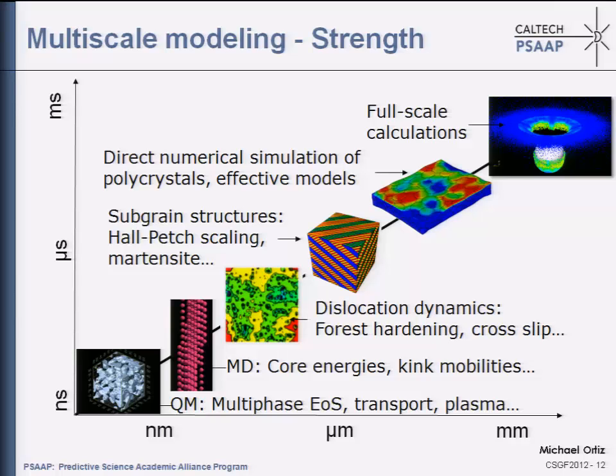So say, for instance, you're trying to characterize the strength of materials. Okay, so how do materials deform at high levels of stress and temperature and strain rate, for instance? Your global simulation may be at this level, so now you start looking down length scales and time scales. In a typical metal, you begin to see the polycrystalline structure. So you see that, in fact, these material points are not points at all, but themselves have quite a bit of structure. The first level you encounter at the SEM level, for instance, is the polycrystalline structure. Then if you look within individual grains, you find that the behavior of each one of these grains is in fact far from being homogeneous.